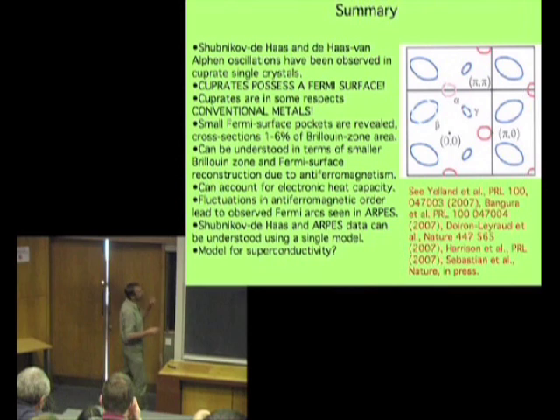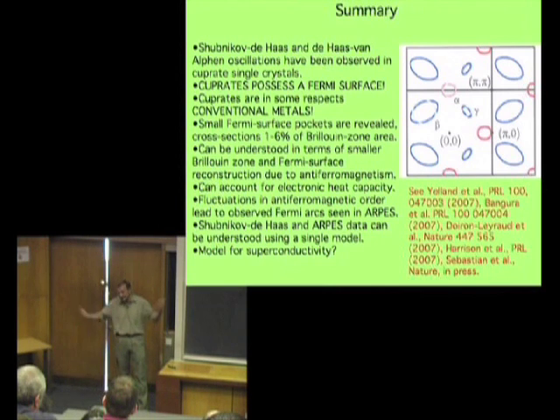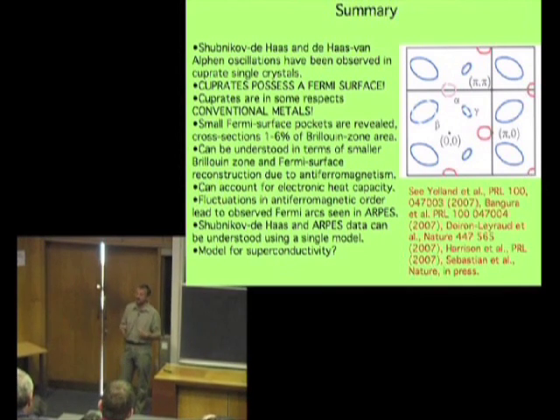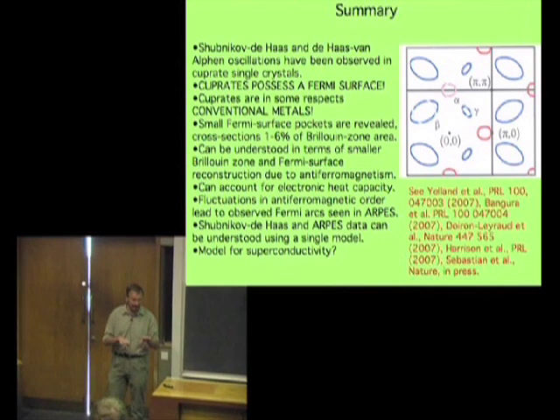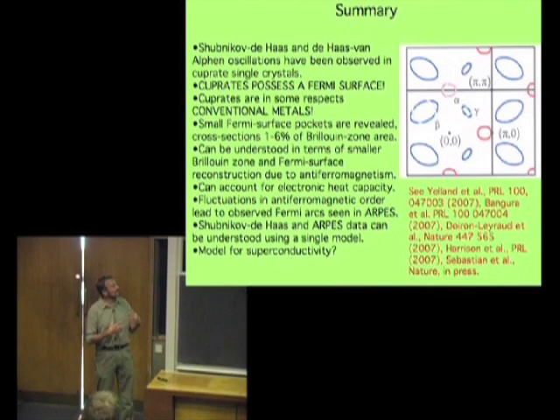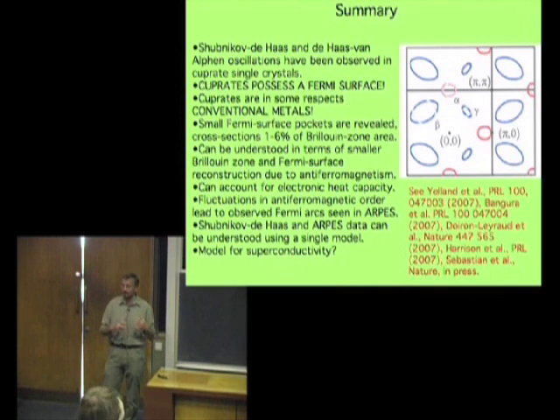They do stripes and checkerboards and things like that. My belief is that for this method of superconductivity to work, the electron-phonon interactions shouldn't be so strong. If they're any stronger, what will happen is you'll have something like a charge density wave rather than a spin density wave, and that will act in competition with the superconductivity. So all of these other materials like nickelates have stronger electron-phonon coupling constants, and so you get checkerboards and stripes, which are basically, I think, in spite of the differing terminology, charge density wave-like phenomena, which get there before the superconductivity does. And the cuprates are mostly of a sort where the electron-phonon coupling is not so strong that it gives you an alternate ground state at low temperatures to this one.